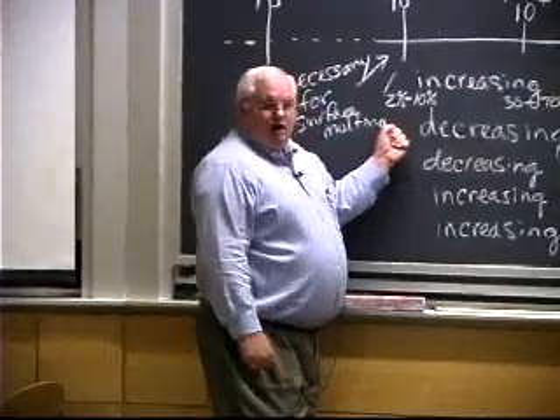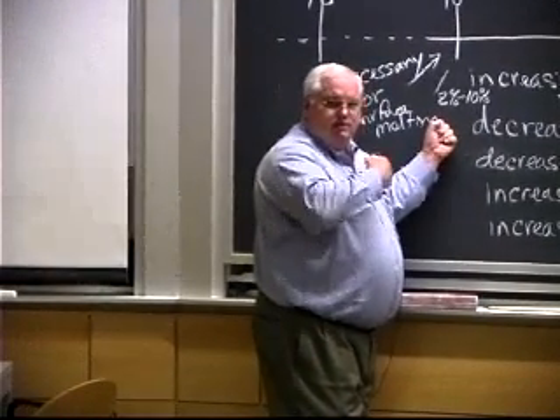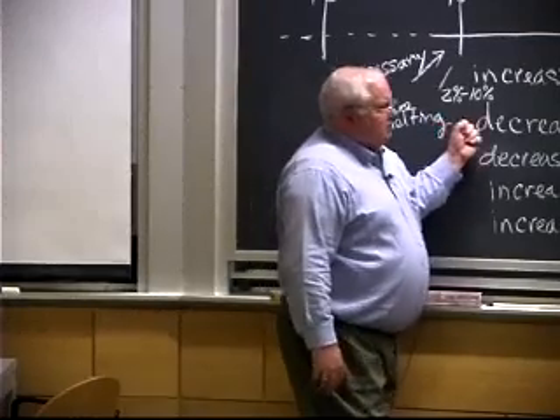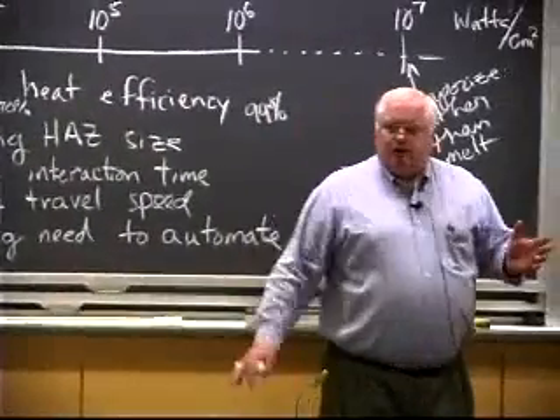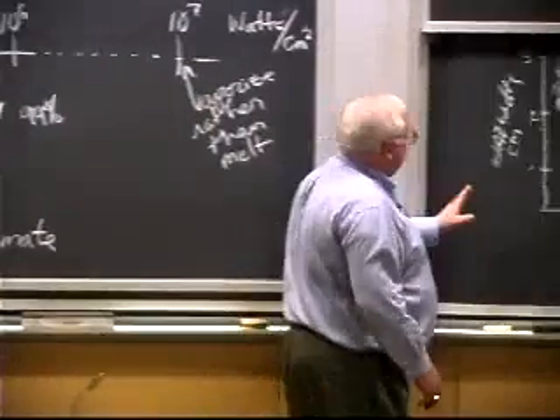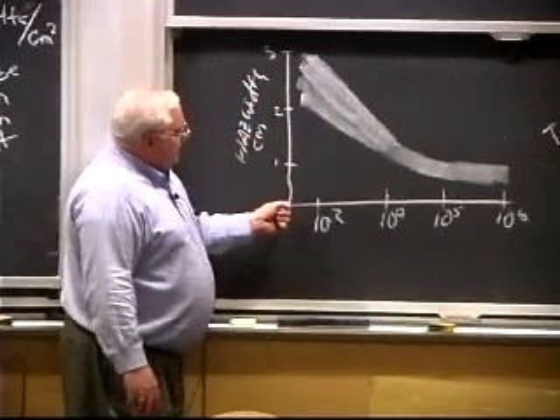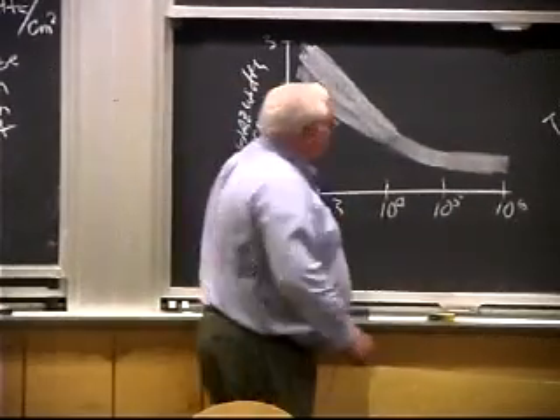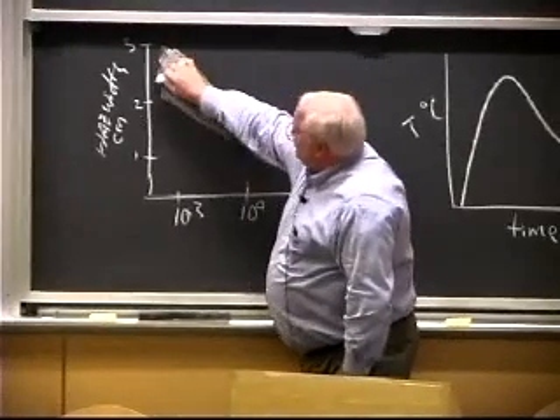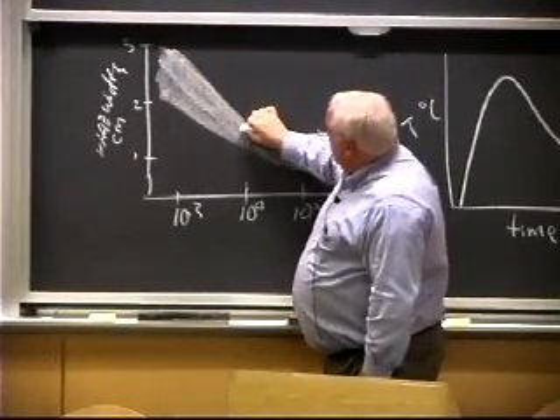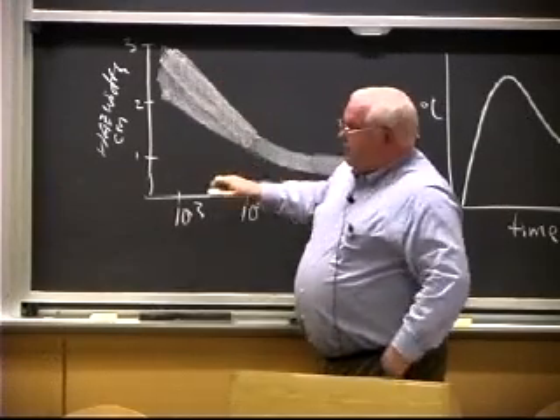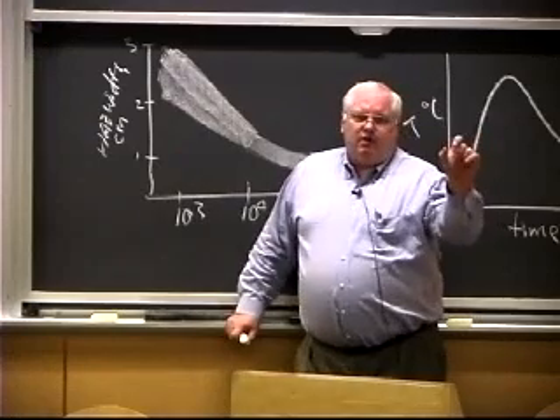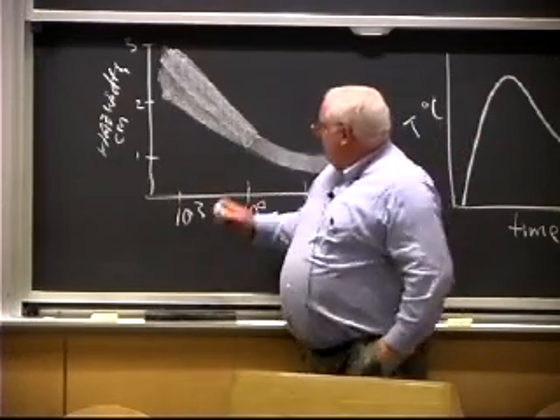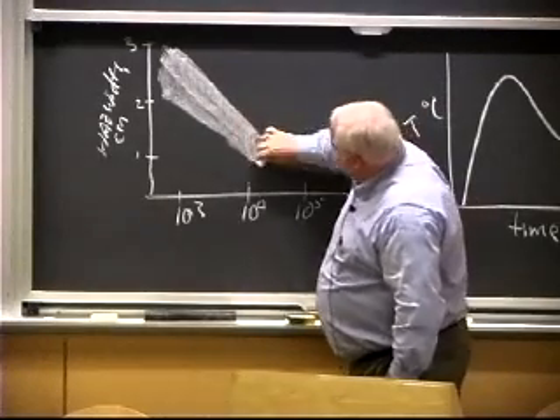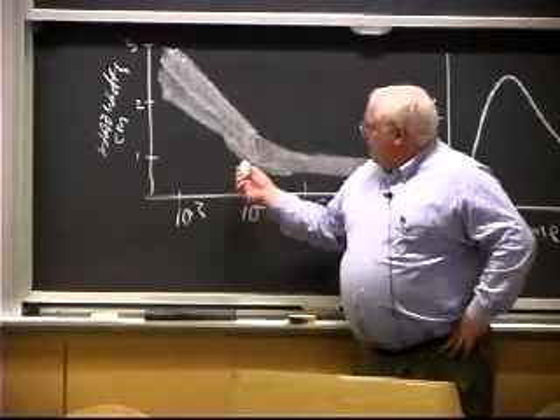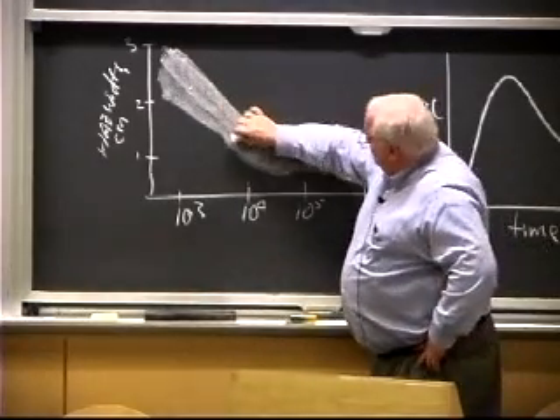It turns out over here, where you're wasting a lot of heat because it's a slow process, letting heat diffuse into the base material, you get a big heat affected zone. And over here, people say you get no heat affected zone. Well, that's wrong. And the reason it's wrong, if I actually look at heat affected zone width in centimeters, and I have this watts per square centimeter log scale down here, people basically look up here and say, gee, for the slow processes like oxy-acetylene welding or arc welding in here, I'm going to get a much larger heat affected zone. I can have heat affected zones 2 or 3 centimeters in width with something like oxy-acetylene welding. But it's going to be down on the order of a centimeter or less. Actually, it should be millimeters down in here, with arc welding. And people just kind of extrapolate that and say, well, it goes to 0.